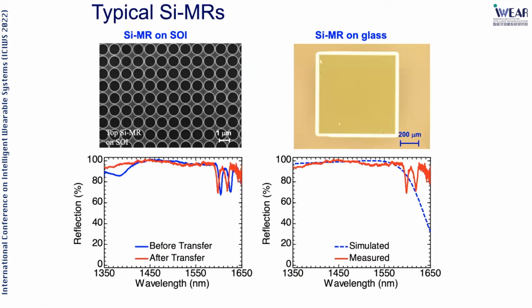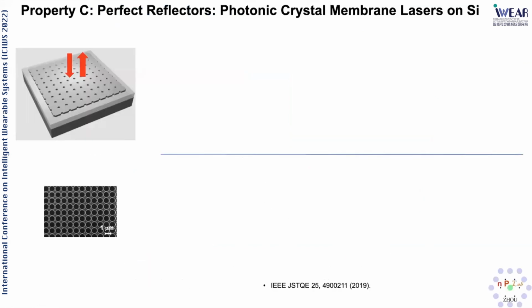And lastly, we also looked into the broadband reflector here. It's very thin, like in this case, 340 nanometer thick silicon. We could get 100% reflection. And we built on silicon, and we also built on glass substrate. You can see here, some of the works are also collaboration with John, where we can achieve a very high performance reflector with a very thin platform. And you can imagine it can also be flexible.